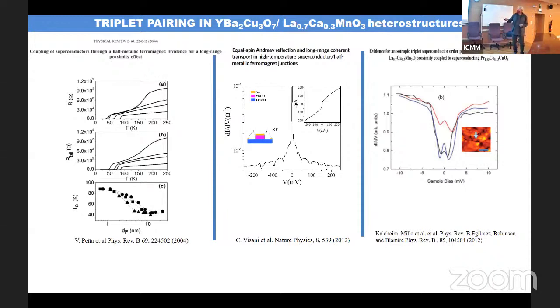You may see in this paper, from 2004, this is Vanessa Peña, one of my students. We found that in superlattices, at that time everyone was doing superlattices, right? And you may remember, Jose Luis, that we were measuring these things. What we found is that changing the thickness of the ferromagnet, we got a modulation of the critical temperature in a wide thickness range of the ferromagnet. At that time, we interpreted this as an indication for a long-range proximity effect. A bit speculative, to be honest.